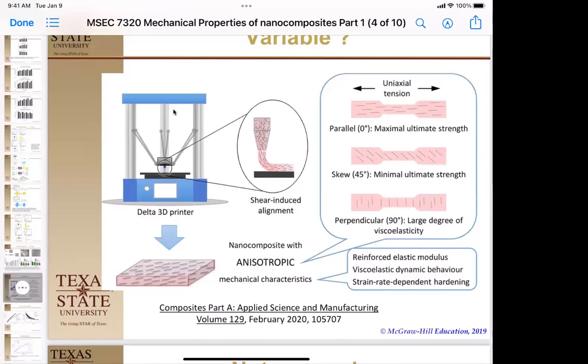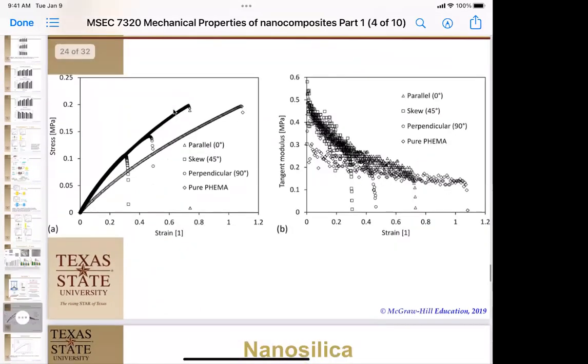So what happened? Well, if we look at the data, right here we get some interesting stuff. The modulus didn't change. The pure polymer itself is weaker than all of the composites. Okay, the one that's 0 degrees that's parallel is the highest ultimate strength, but the modulus is the same. The one that's perpendicular, 90 degrees, was in the middle. I don't know how to explain that one. And then the one that was askew, 45 degrees, was the weakest. Almost like those things were trying to create a shear plane across that diagonal.